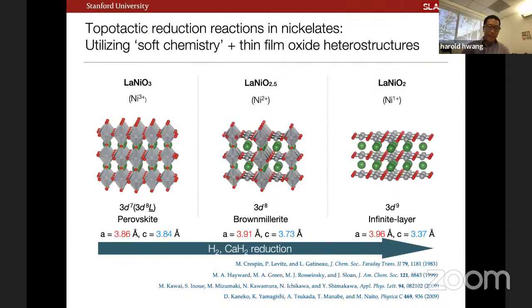And one can do a series of deintercalation reactions where you can pull out rows of oxygen. So you can go from 3+ to 2+ and stabilize this brownmillerite phase. And you can go further from 2+ to 1+ by taking out this other apical oxygen row and make this infinite layer structure. So this bulk chemistry itself is actually quite challenging, and people are making exciting progress to this day on this problem. A second key development in 2009, which we will again utilize, was the observation that you could perform these reduction reactions and have some benefits of stability in oxide thin film heterostructures.